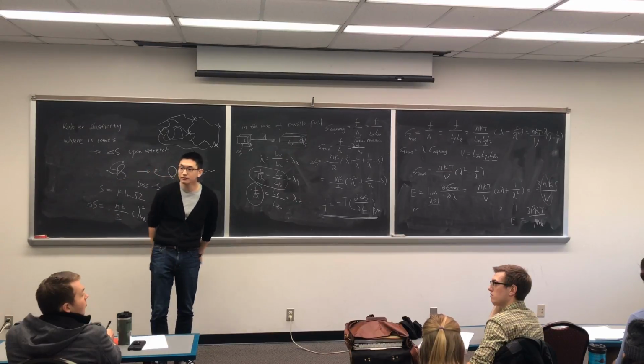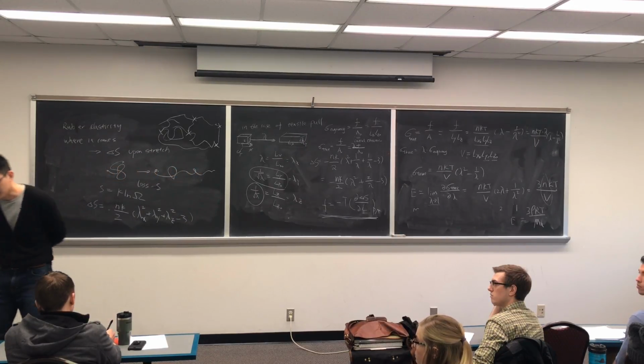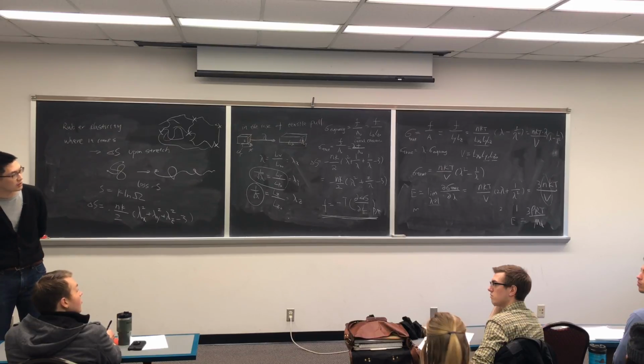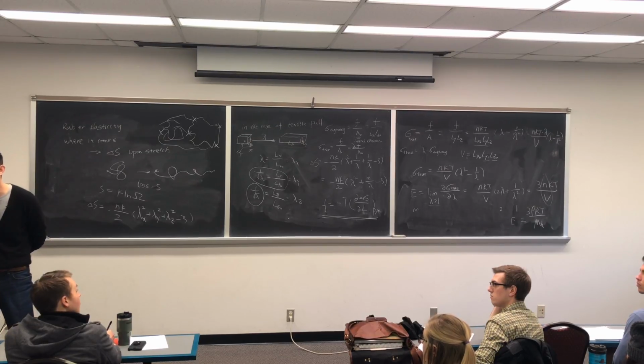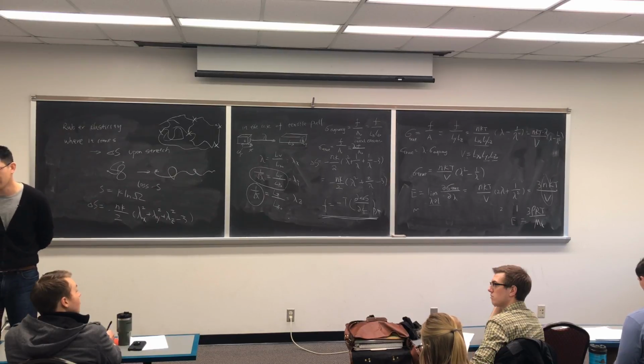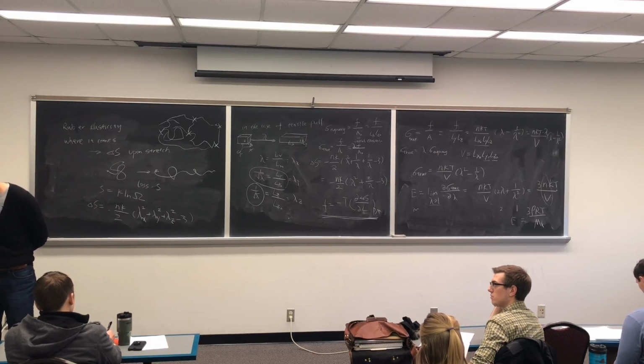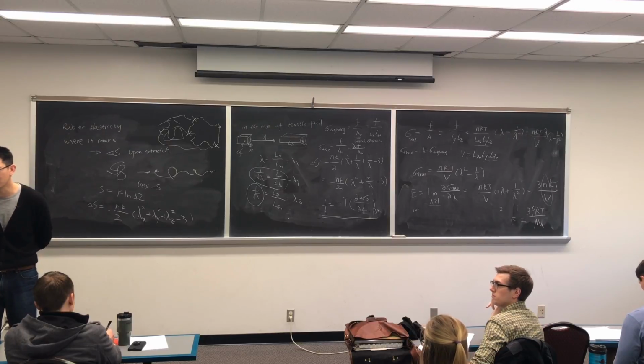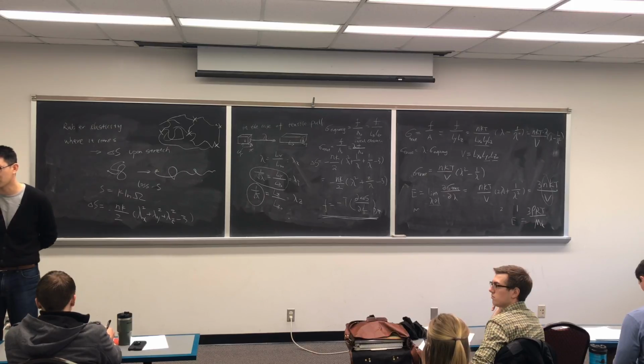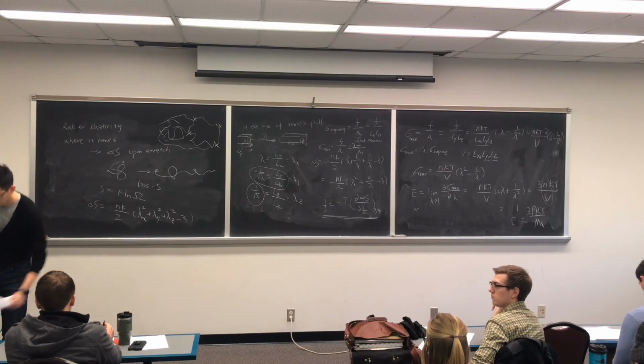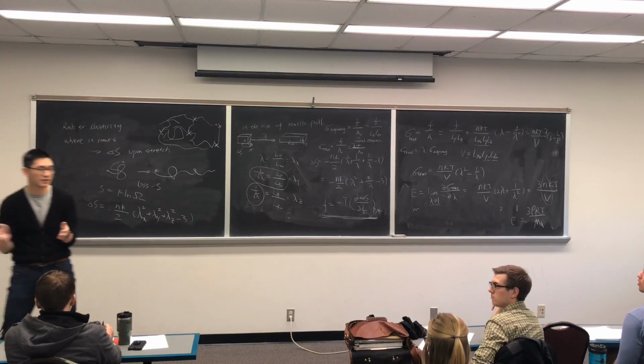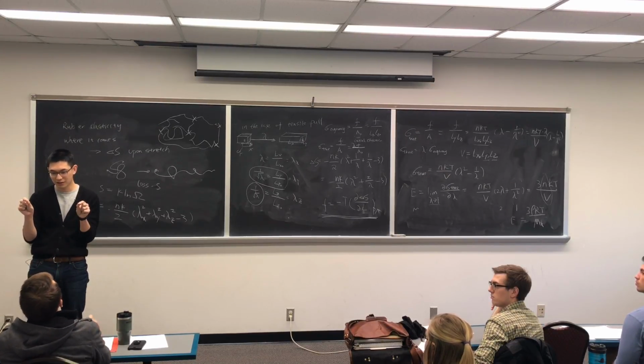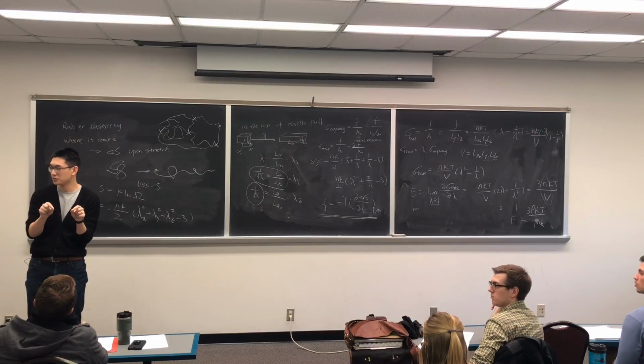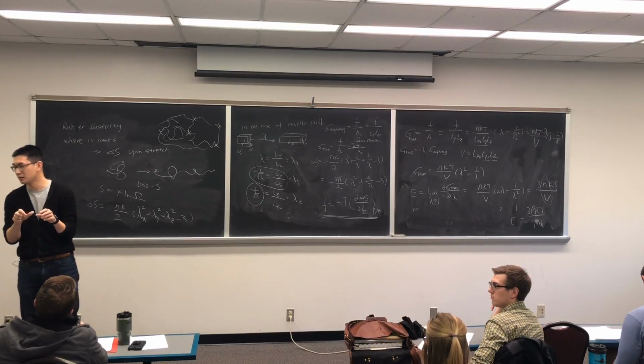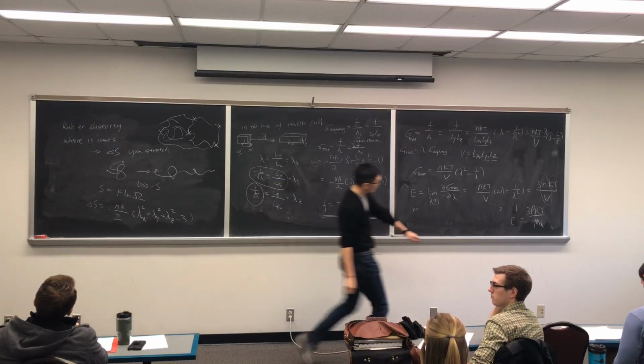Wait, can you repeat that? You said what? Can you repeat that? Yes. So you can get the crosslink density, n divided by V, which is how heavily you crosslink it, right? That's one way you can view the system. There's a second way you can view it physically, which is the molecular weight of your segment between each crosslink point. They're talking about the same thing. If you crosslink the polymer 10 times more dense, the distance between two crosslink points will reduce by 10 times. It's reflected by the molecular weight, or Mx here, okay?